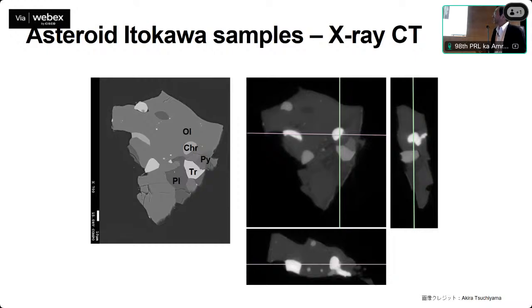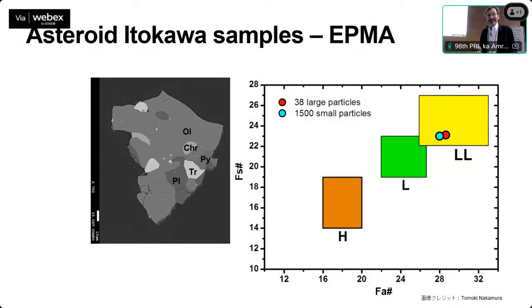So we analyze the composition by EPMA. There is a state-of-the-art EPMA also installed in this institute. And using the EPMA, we analyze the iron composition of olivine and pyroxene. The horizontal axis is the composition of olivine, shown as the fayalite content. The vertical axis is the iron composition of pyroxene, shown as the ferrosilite number. And the average of more than 1,000 particles is here.